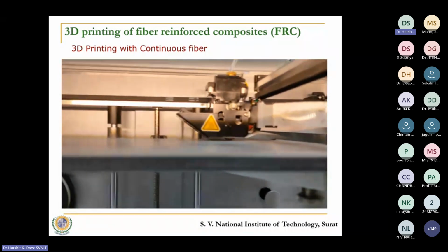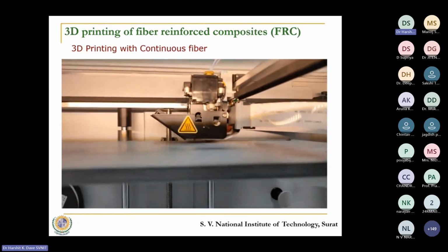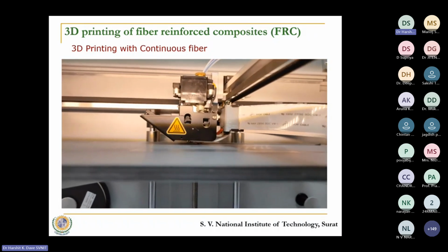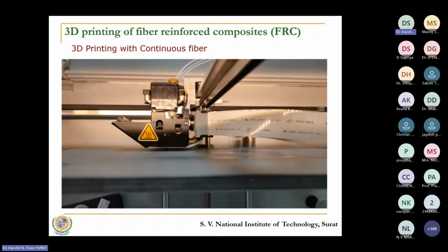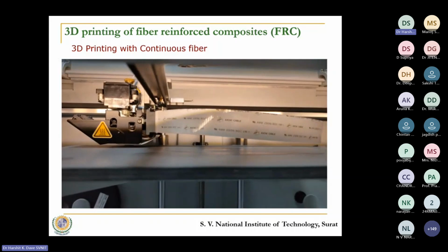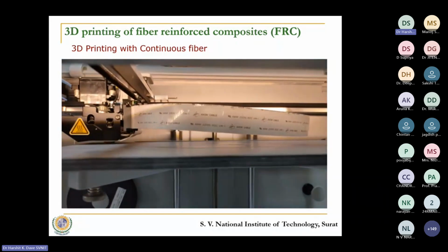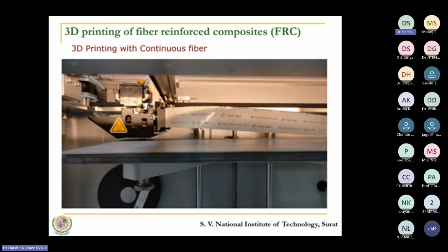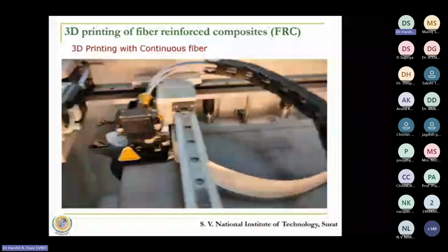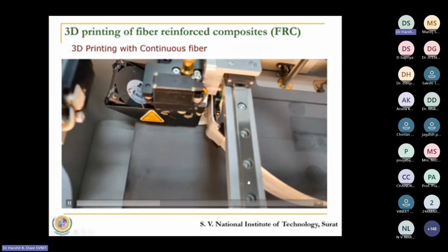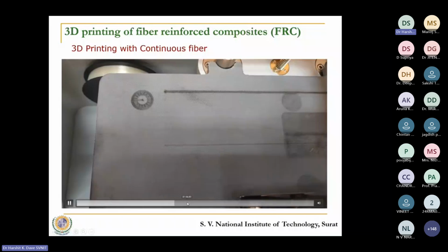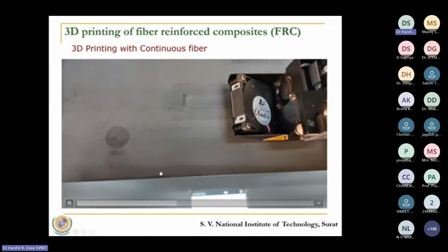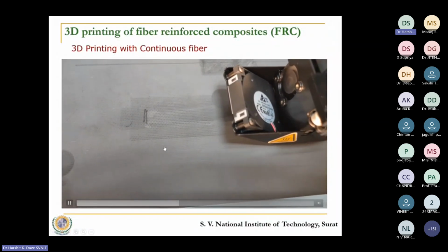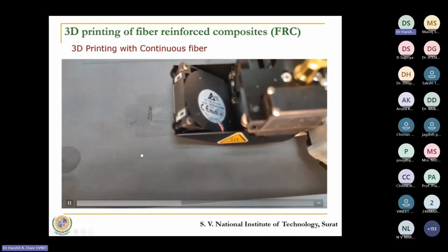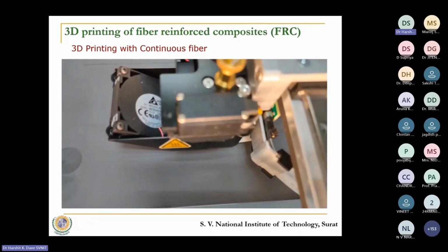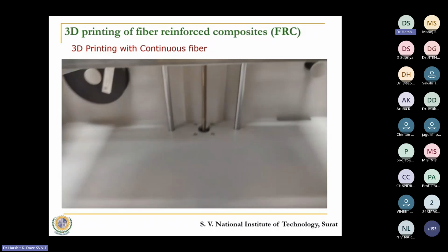So you would observe that some first boundary is created with the selected polymer, and then some sort of fiber is deposited for checking, and then once we approve, the initial part starts getting printed. Once this is initiated, I'll slightly skip ahead. You can see those first 2 layers are created, and this is the original part now being created, a flexural part.